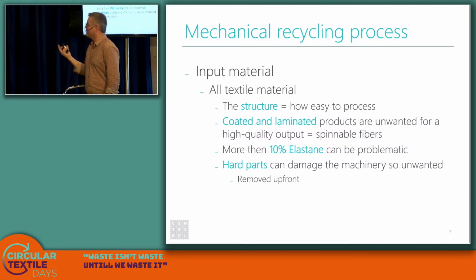First of all, mechanical recycling processes. You can throw practically anything into that. But what you throw in is also the thing that comes out. So depending on the structure, knitted fabric is way easier to process than a woven fabric. If you apply a coating, you make it very difficult to obtain fibers, practically impossible. So a high-level output is not possible when you have a coated fabric. You can put it in non-wovens for insulation or grind it and use it as a filling material. Elastane at around 10%, if you go higher, can be problematic. Hard parts can damage the machine, so you want to remove them, especially with the heavy technology.